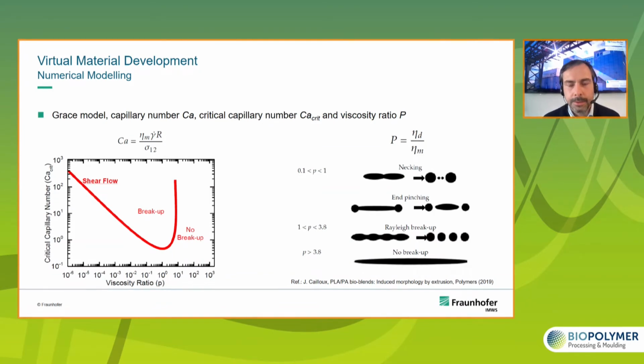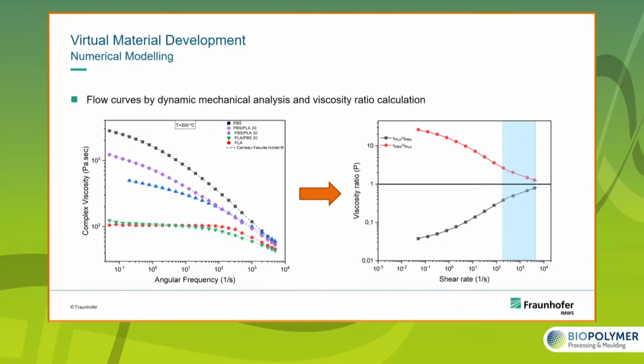And what you can see here on the right side is what happens if we have different viscosity ratios of the matrix and the dispersed phase. So if the viscosity ratio is close to 1, you will have this Rayleigh breakup, which is a deformation of droplets to fiber-like structures, and then the breakup to smaller droplets. If the viscosity ratio is smaller than 1, we have this necking effect. And if the viscosity ratio exceeds a factor of 3.8, experimentally, you won't find any breakup anymore, and you will stay with big particles. What you can see here are the results of our rheological experiments on PLA and PBS.